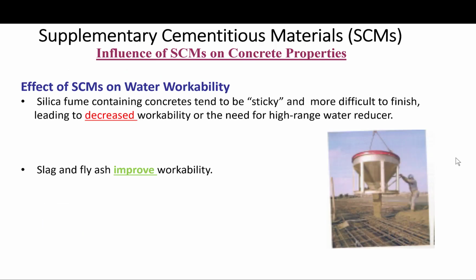Okay, the effect on workability, which is also a big deal. Silica fume-containing concretes tend, as we said before, to be sticky and more difficult to finish, leading to decreased workability. In that case, we will need to add high range water reducers in order to improve workability, rather than adding water. We have the blessing of using these admixtures, which we will talk about in the next module of the class. Slag and fly ash generally improve workability.